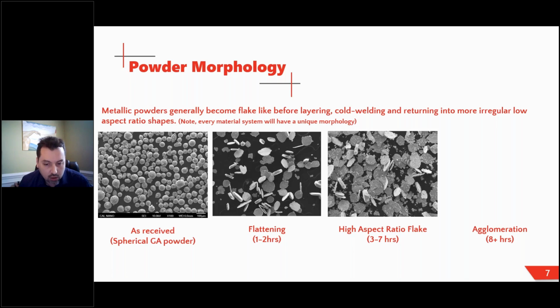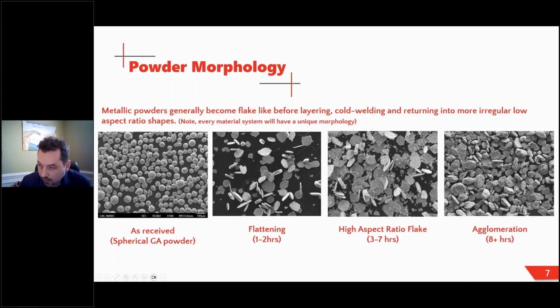As the material gets stronger and is forged and stronger, those structures are going to get stronger, and therefore they're actually going to start to agglomerate back into irregular shapes. This process is, again, going to be unique to the material systems. If you had a really hard material or strong material like a super alloy, this result will happen faster given the stronger nature. The milling parameters, the speed at which we're milling, the type of milling, the media we're using is all going to have an effect on this. But the main message here is that we are able to control the powder size.